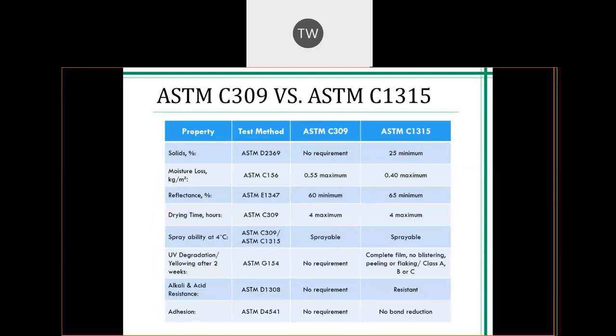So this slide serves as a comparison chart to understand how these two very important specifications for external curing of concrete compare. As I mentioned, ASTM C309 has no solids requirement. However, ASTM C1315 has a 25% minimum. Higher percent solids material, though, can be extremely difficult to deal with. Your contractor needs to be educated enough on using the right sprayer and right tip. Another thing, ASTM C1315 has a much lower moisture loss requirement. ASTM C1315 has a higher reflectance percent. ASTM C1315 has a UV degradation, alkali and acid resistance, and adhesion requirement. All in all, ASTM C1315 is a more stringent requirement than ASTM C309.